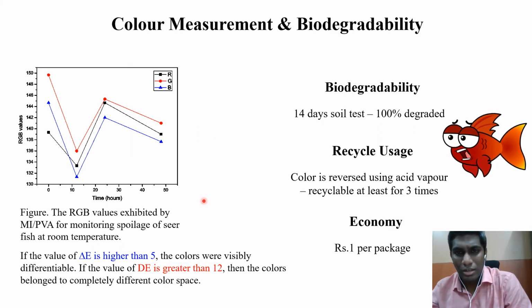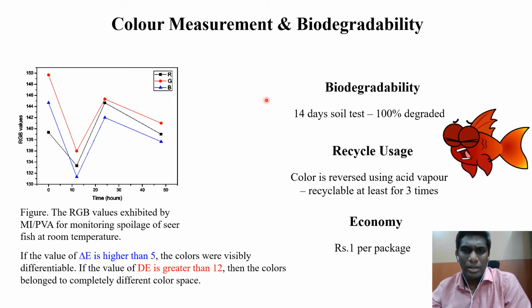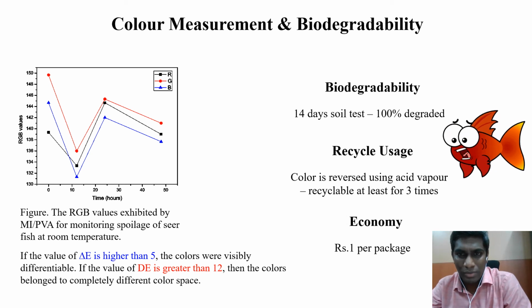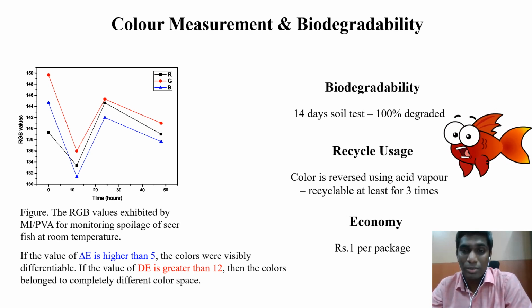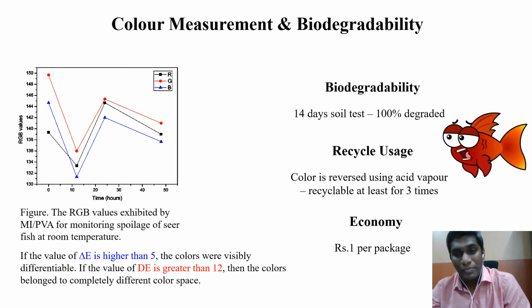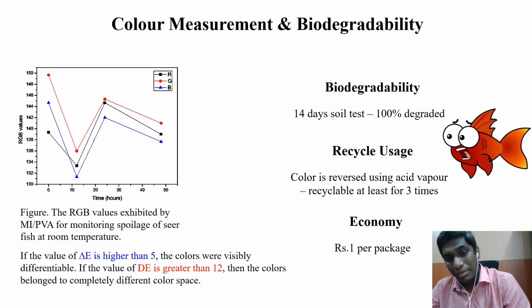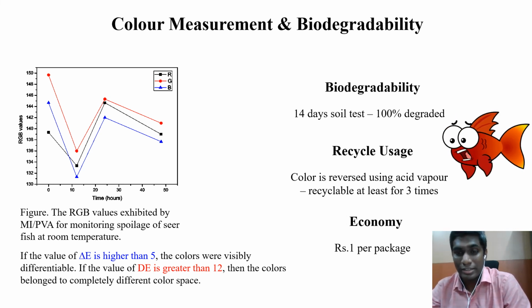We also checked the biodegradability of the halochromic thin film through the soil test, and we found that the halochromic thin film sensor is completely degradable within 14 days of incubation in the soil, fertile soil. And we also checked the recycle usage of the thin film. We find that the color of the thin film can be reversed using the acid vapor, and it can be used at least for 3 times.